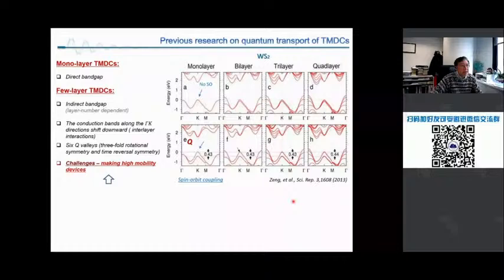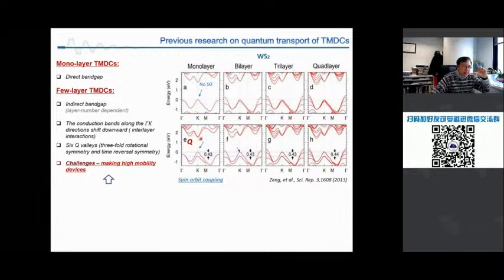All right. And if I show you the calculation of the band structure, you should be familiar with this, and then understand what I'm talking about in transport. For monolayer, you have 1 band; bilayer, 2 bands; trilayer, 3 bands. But once you consider spin-orbit coupling, this 1 band splits slightly up and down, and the valence band up and down. All right, and a similar situation happens for different layers. And if you look at the Q valley, once the layer number increases, the Q valley shifts down.